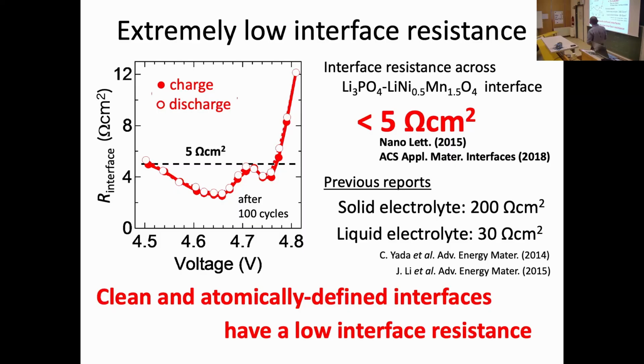This is a picture, and this is not today's topic, so I will not go into the detail. Anyway, we show that the ionic conductivity across the solid-solid interface can be very high. That is very good for solid state battery research. The interface resistance can be lower than that of the liquid lithium-ion battery system. So a solid-solid interface can be better than a liquid-solid system. This is a very good sign for solid-state batteries.